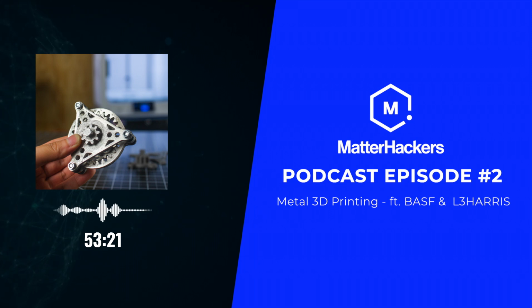Correct. Cool. We all love watching a first layer. Any tips of the trade for getting that first good layer and then therefore a successful part? Well, the main thing with the metal, and it's not just going to be on the first layer but throughout the part, is that any air gaps or voids in your part are potential failure points through the debinding and sintering process.